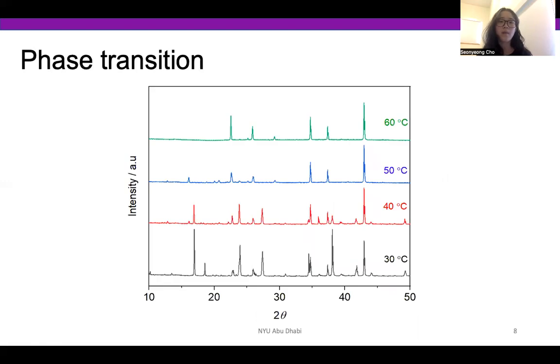And then powder X-ray diffraction was conducted in order to confirm this phase transition. So it showed that the material experiences structural changes with increasing temperature, and these changes appear to be gradual over a wide range of temperature, yet showing a very drastic change between 40 to 50 degrees Celsius, where the order to disorder phase transition takes place.